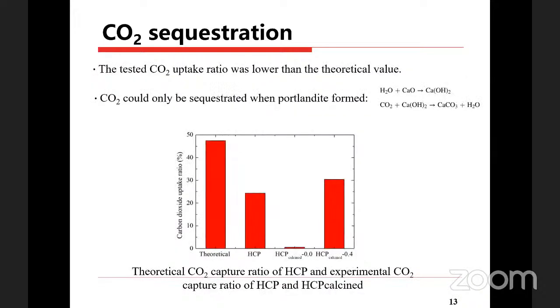That is some chemical formulas, quite simple. The tested CO2 uptake ratio was quite low, lower than the theoretical value, because there is a lot of water loss during this process due to evaporation, and the dense layer formed on the surface of the concrete may prevent further carbonation. Meanwhile, we can find that CO2 could only be sequestrated when Portlandite formed. So that's why the role of water is quite important during the recarbonation process.